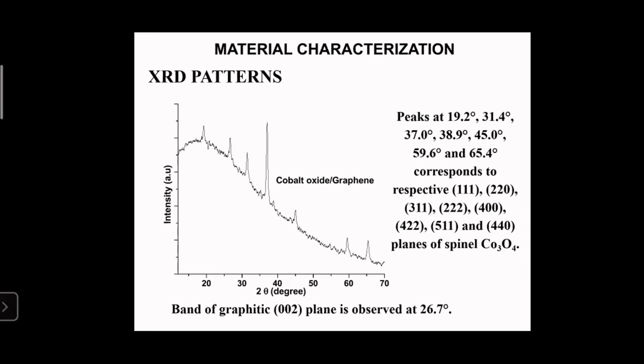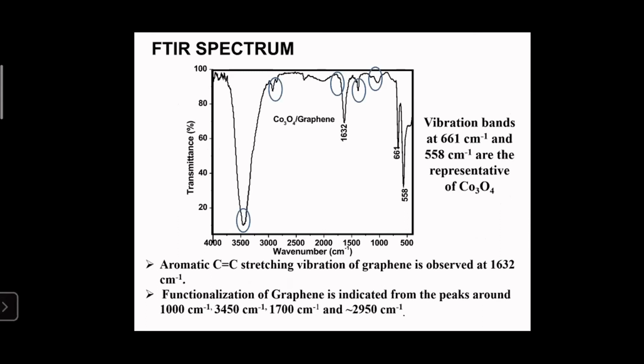In addition, the graphitic peak is also visible there, but it is not shifted towards the left as in graphene oxide, because there are no functionalities present on the surface of the graphene sheets. But the broadening of the peak suggests edge functionalization. And the functionalization is further proved from FTIR spectral analysis. The composite shows peaks specific for Co3O4 and aromatic C=C stretching, and in addition, it confirms the functionalization of the nanocomposite by the peaks around 1000 cm^-1. It corresponds to C-O-C as well as C-O-H linkages, and the peak around 2900 cm^-1 indicates C-H, aliphatic C-H or carbonyl C-H. A carbonyl peak is also visible around 1700 cm^-1. These peaks indicate the functionalization of graphene.